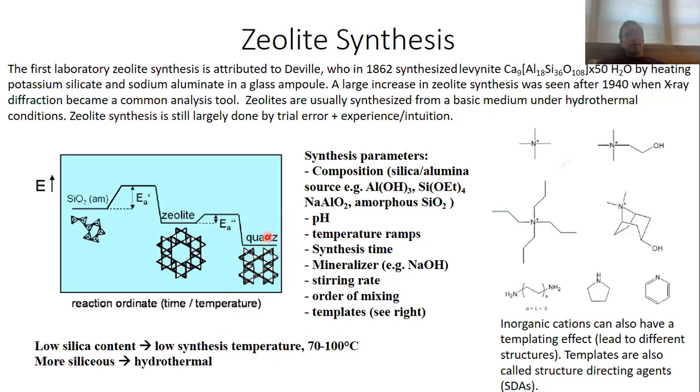So you often need to apply relatively mild temperature conditions, because your zeolite is only metastable. If you make the conditions too harsh, then often the activation barrier for the conversion of the zeolite into quartz is overcome, and your zeolite synthesis actually fails.